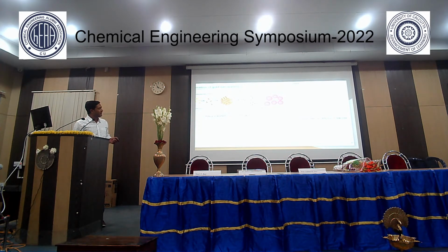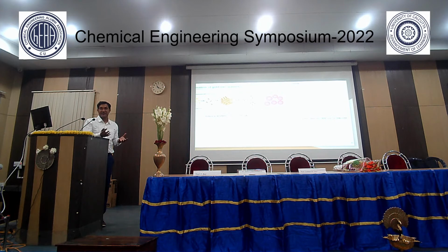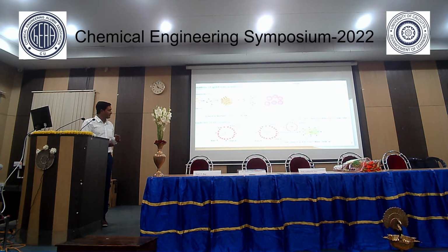Or it can be another phenomenon where you have put in surfactants. The surfactants will individually bind these metal ions, and then they will grow. That is another way to precisely define the size and shape of the nanoparticle. In the electrochemical process, you have the ions in micelles, and then you reduce the ions to form the nanoparticle inside that micelle.